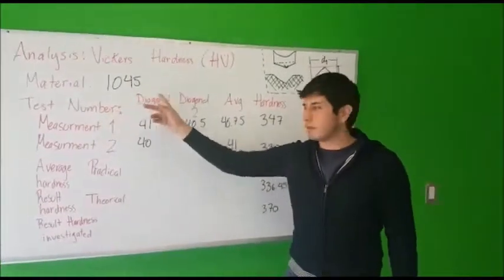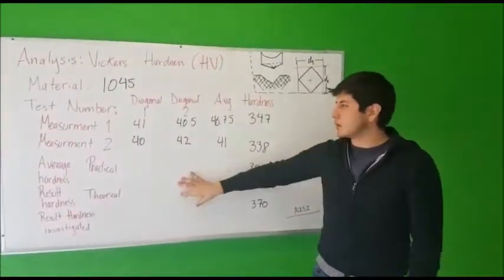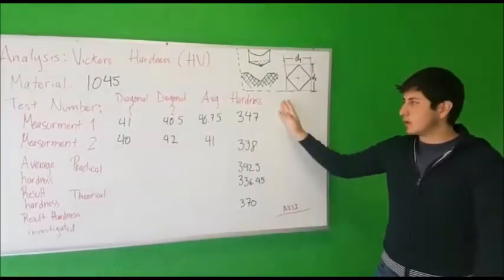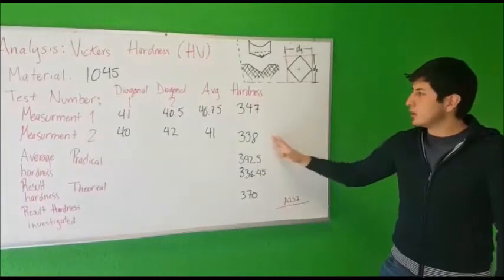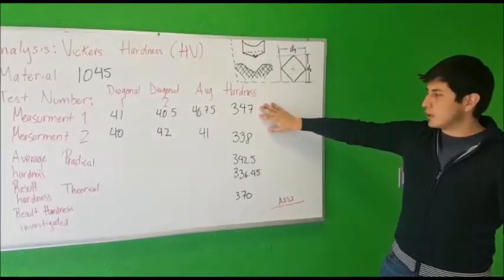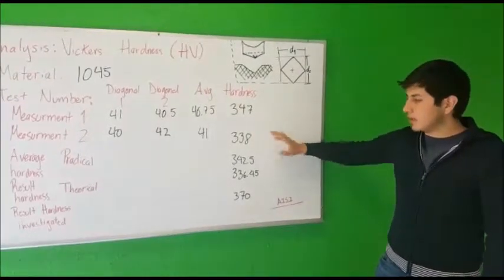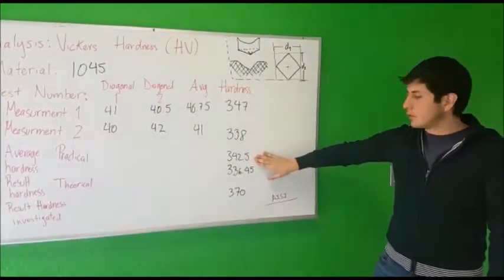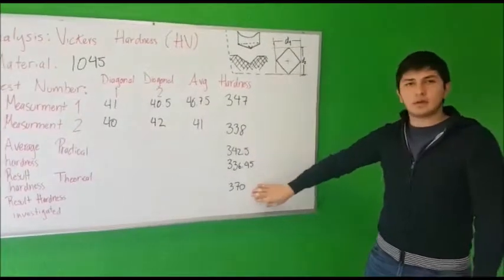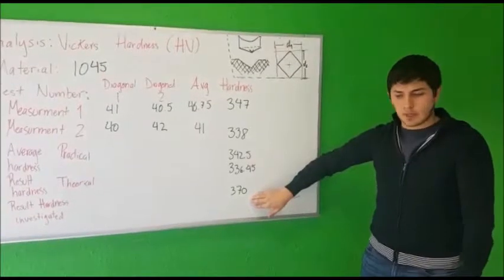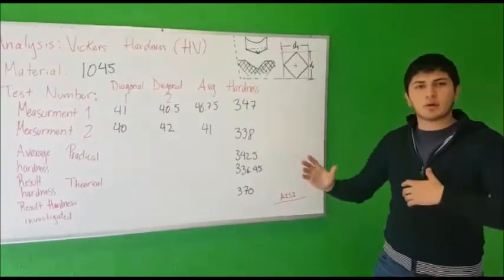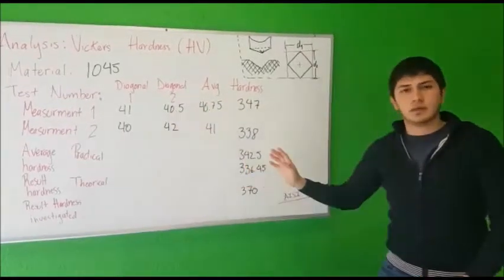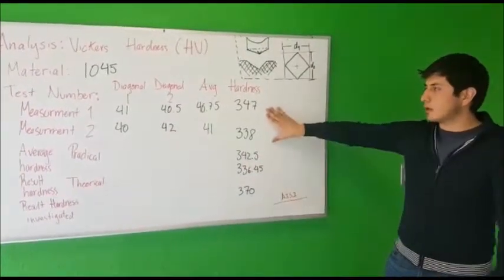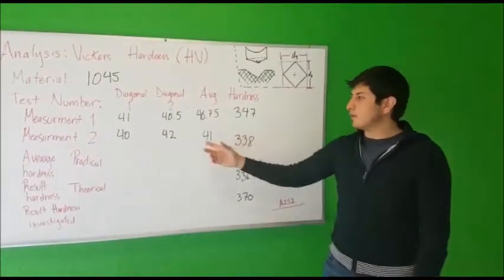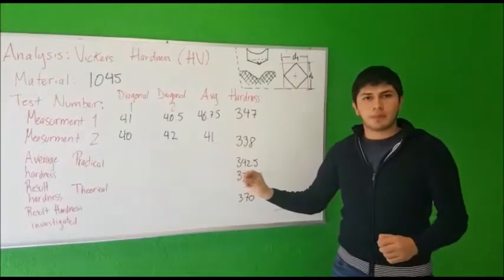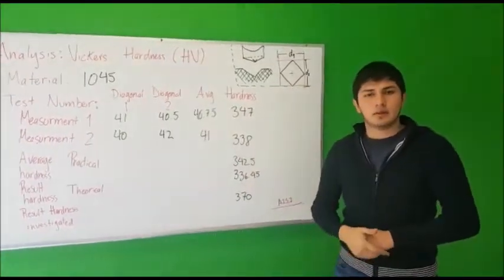Then for the steel 1045, we get this measure, where the unit of hardness is kilogram per square millimeter. Here we have 347, then 338. The average of those two is 342.5, and the real value is 370. If we compare the steel 1045 and the steel 1018, we can see that we get more hardness here because the diameters of the indentation are smaller than the 1018 steel.